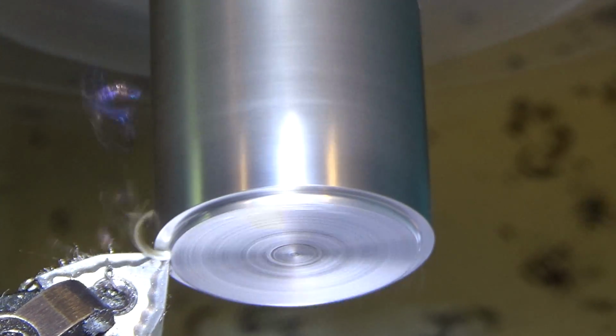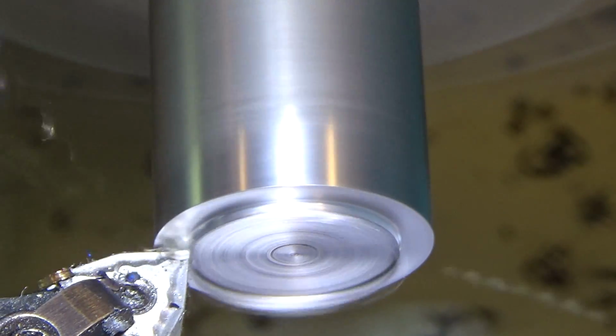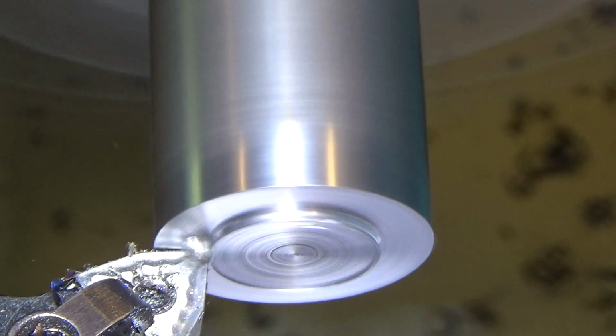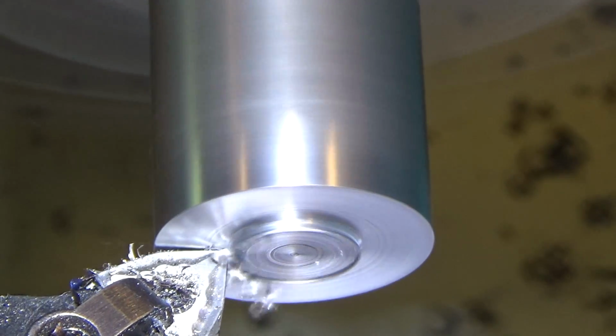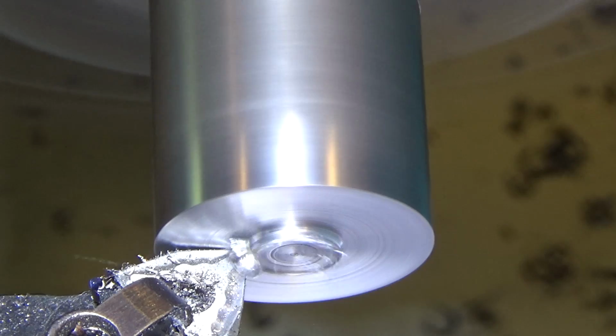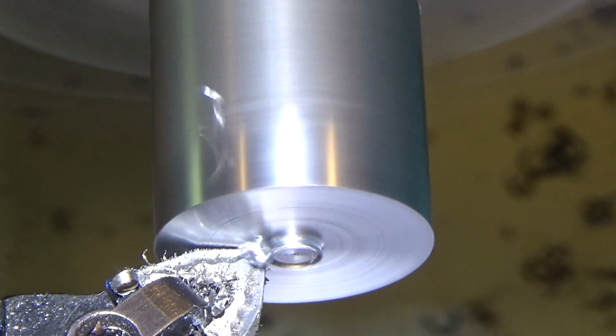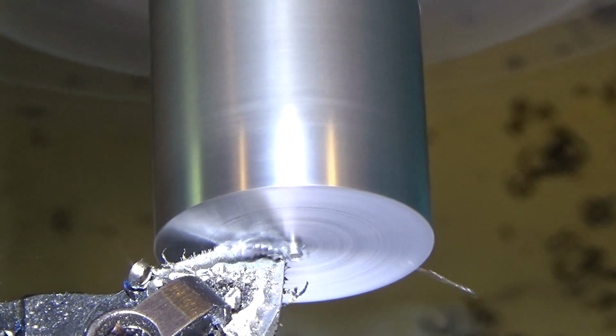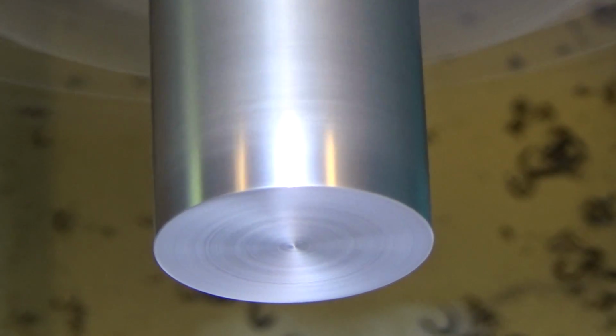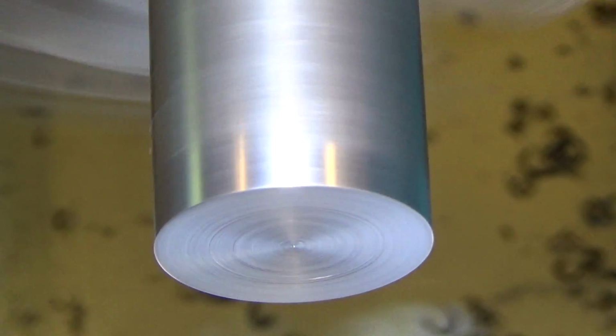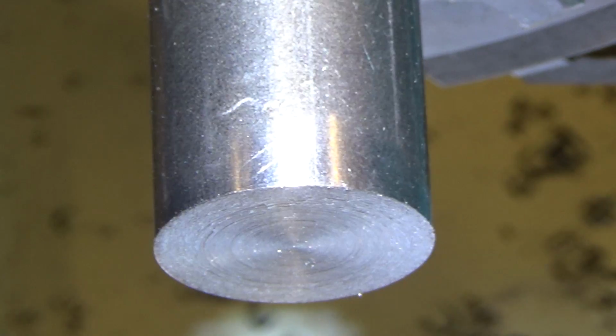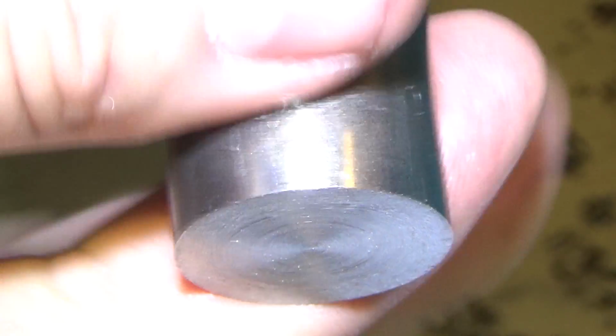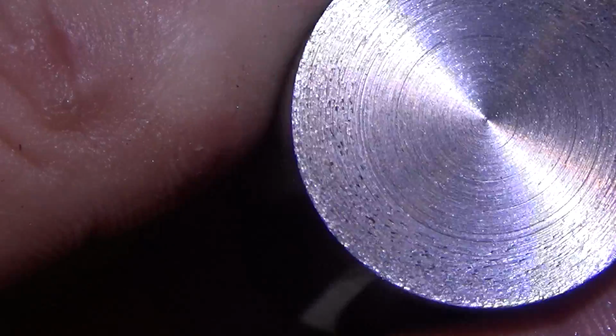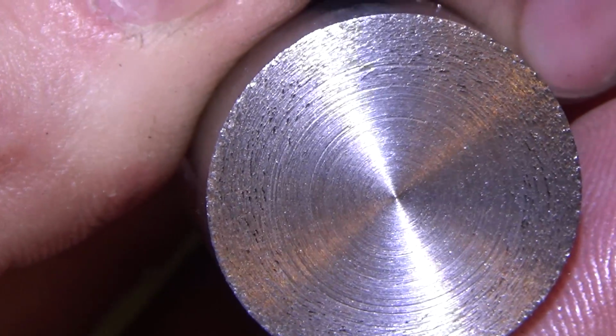So there's a 30 thousandths pass. The chips are breaking well, and they're blue, so it should be a good situation. Alright, so if I had to guess, in the annealed state the grains are really large, so they tend to tear out a little more and make an uglier finish. If you notice, it's a pretty ugly finish. I mean, it's a lot better than it would be if I went slow, so I'll do another pass and go slowly for you so you can see the difference.